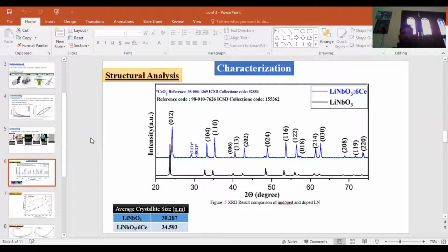In the characterization part, I used many characterizations to get the results of what I have performed in my research. Very firstly, I shown here the structural analysis part. For the structural analysis, I used XRD characterization, and in figure 5, I shown the comparison between the pure lithium niobate and 6% cerium doped lithium niobate, and I found that there are some secondary phases present because